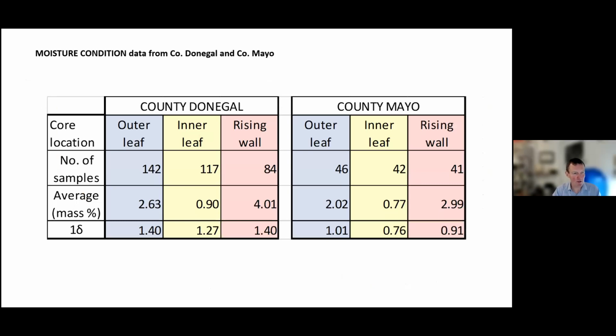What I want to point out is that the average of all this data for the outer leaf in Donegal is about 2.63%. It's a bit higher than the average for the outer leaf in Mayo. So this suggests that the Donegal concrete, for want of a better word, is more likely to absorb water than the Mayo stuff, but the Mayo stuff is not far behind it. It's all what I would call wet to saturated, really.